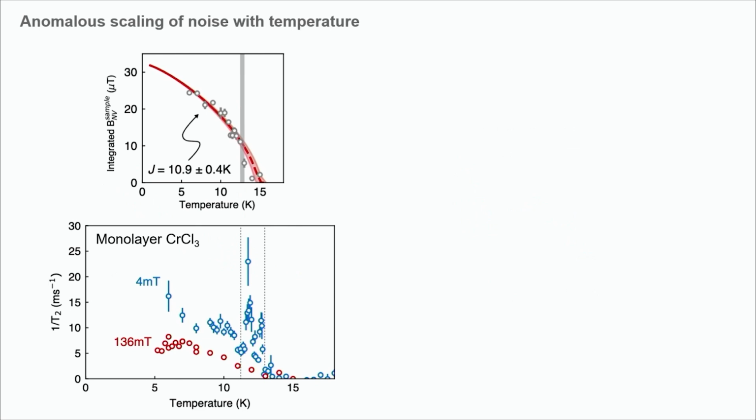Shown on the top here is a measurement of the magnetization of the sample, essentially the ferromagnetic moment of the sample as a function of temperature. So it's got a fairly low transition temperature, something like 12.5 Kelvin. But as you cool it down, the magnetization progressively freezes. Presumably, you're freezing out the thermal fluctuations in the material.